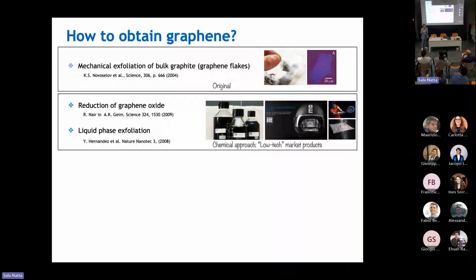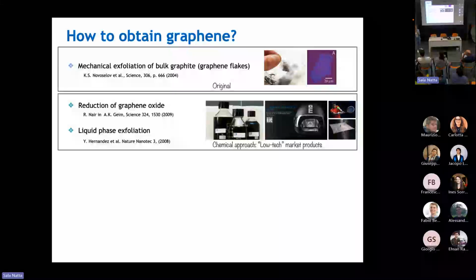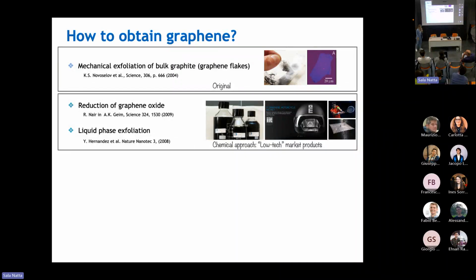Mechanically, you also lose all the properties, because you have friction, you have a lubricant behavior, right? Because graphite is known to slide. We don't have covalent bonds between layers. We have van der Waals forces between one layer and the other layer. That's why you can exfoliate. You don't need to break bonds, okay? Bonds are only in plane. There are no out-of-plane bonds, only van der Waals. And that's why you can have a lubricant material that is typically also exfoliable as a 2D material. But when you make it thicker, it just breaks more easily.